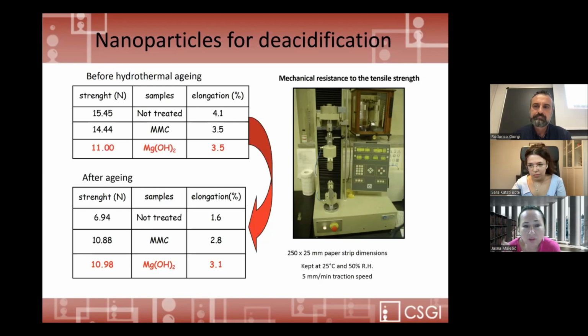Moreover, you didn't show, for example, the case of iron gall ink. We know that the iron gall ink complex is not stable at such high pH values. Even magnesium carbonate was discouraged for use on iron gall ink documents, because it induces discoloration, since the complex is destroyed. And there is another thing. We know that iron gall inks can contain up to the same molar ratio of copper ions, and copper ions increase their catalytic activity with increasing pH values.